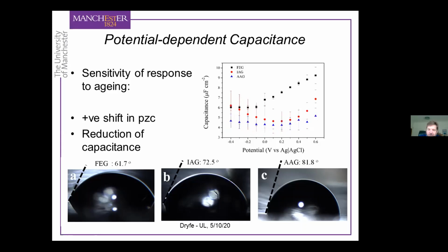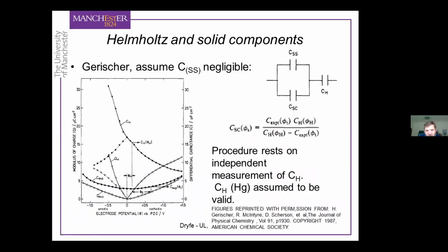And again, these changes in the capacitance are also mirrored in the changes in the contact angle. We go from a contact angle of 60-something degrees for water on the freshly exfoliated material, to 70-something degrees for the material aged in the glove box, to 80-something degrees for the material aged in the laboratory. So basically, the take-home message is that basal plane graphite is very susceptible to contamination. So you have to work with a freshly exfoliated sample very quickly if you want to be fairly confident that you are indeed looking at the response of a graphite surface and not a graphite surface covered with some rather indeterminate organic monolayer.